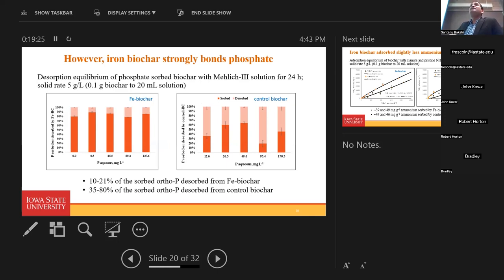When we did the desorption from the phosphate-absorbed biochar using Mehlich-III solution for 24 hours, we noticed that most of the phosphate from the iron biochar stays there. We are not getting too much. You can see from the left side graph that only 10 to 21% of the absorbed ortho-P desorbed from the iron biochar. Whereas for the control biochar, around 35 to 80% of the absorbed ortho-P desorbed. So iron biochar absorbed more and desorbed less. That means it can store the phosphate more than the control biochar.